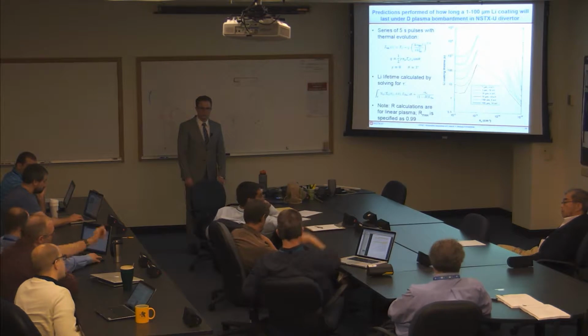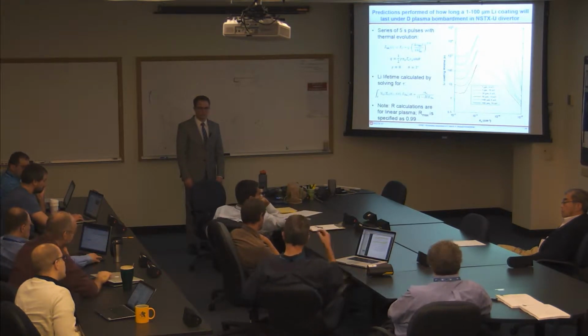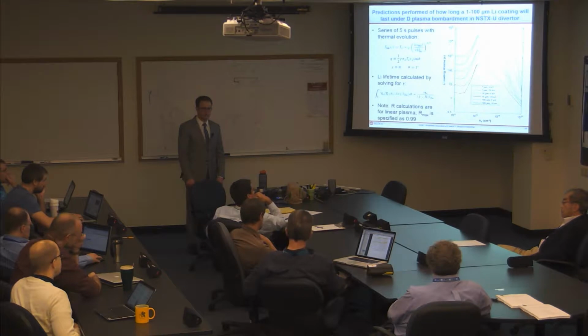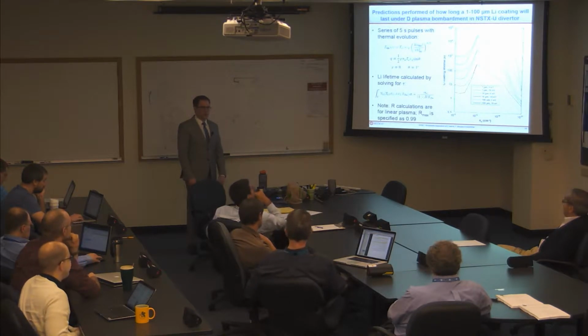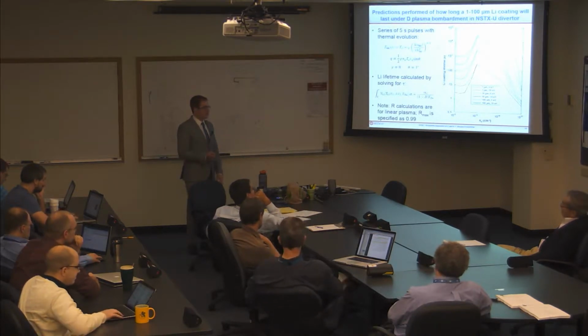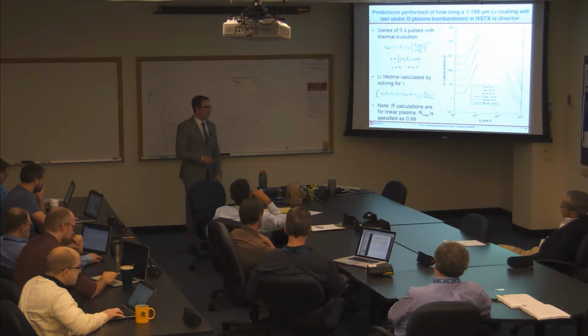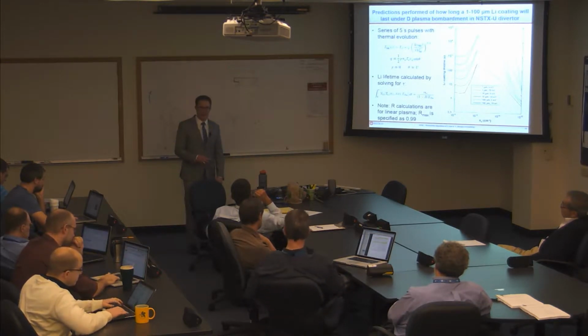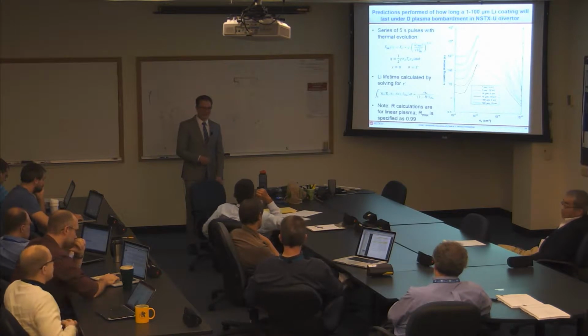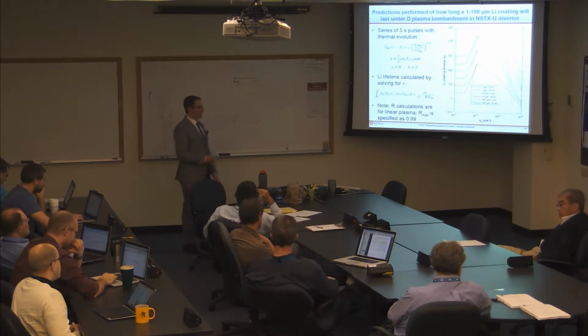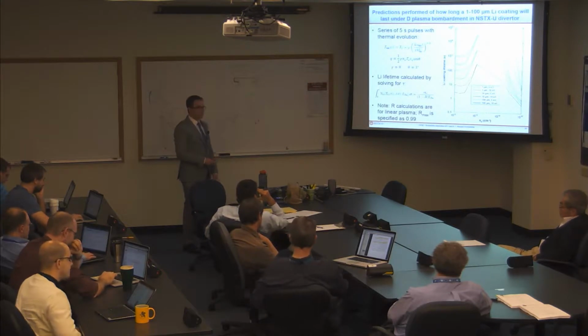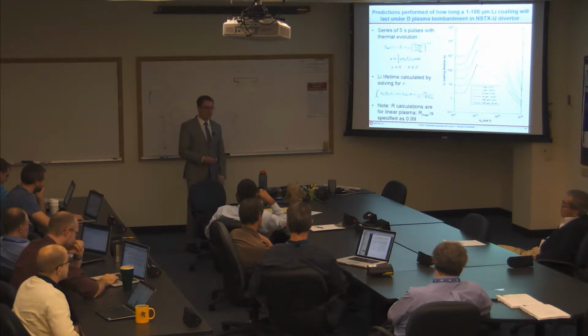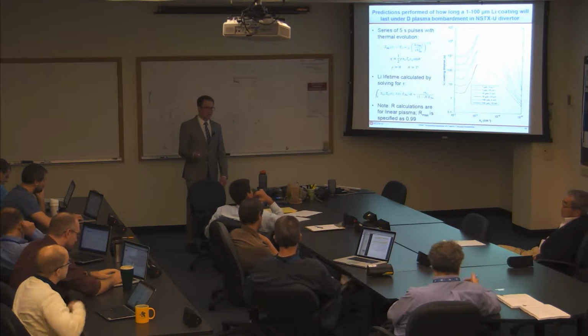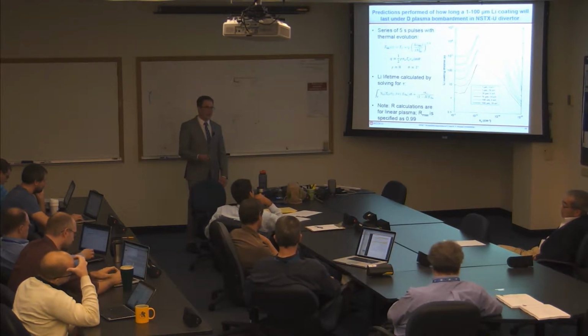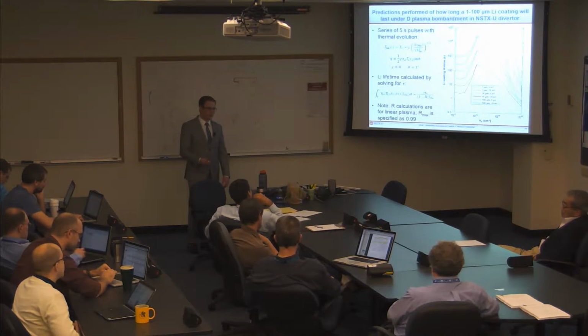Here you're assuming a 3-degree angle of incidence for the field lines, but your experiments and your modeling are done with normal incidence. Why is that relevant? So it is, in some sense, an approximation, but basically at these sort of parameters, you're actually going to have a very high fraction of prompt redeposition. Essentially the lithium ions are going to come around on their first gyro orbit and redeposit basically right under where they eroded.